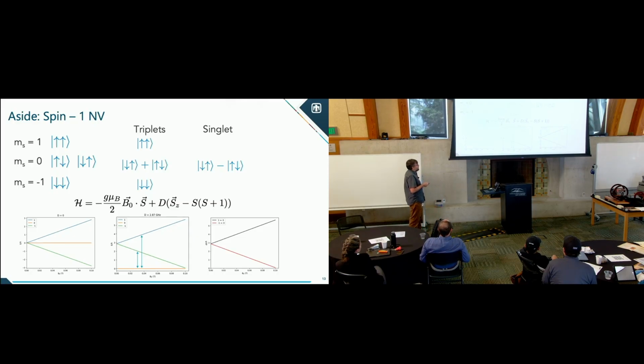And if you look at this difference in energy as a function of magnetic field up to 1,000 Gauss, you have one that increases in frequency and one that decreases. And this is assuming that the magnetic field is parallel to this D axis. All right, and I'll mention that a bit briefly too. But now we have the nitrogen vacancies that have your orbital degree of freedom within the band gap, and now you have a spin state that's sensitive to magnetic field, right?